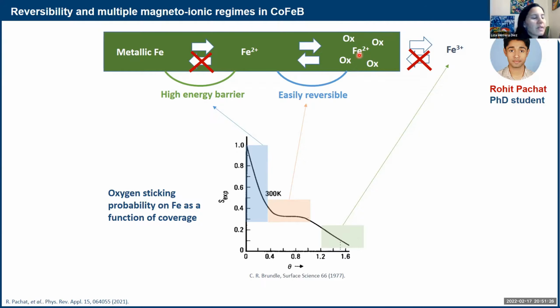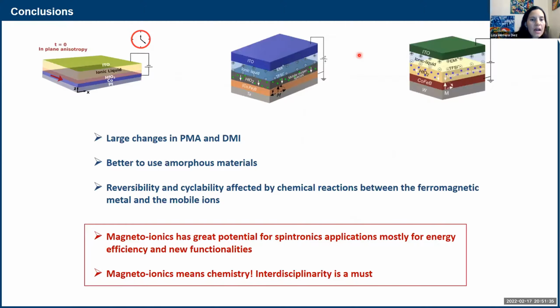I think it's very important to take into account what the ions do in the device. As a conclusion, I hope I could show you that we can get large changes in PMA and DMI by using magnetoionics. That it's better to use amorphous materials, because if we need ions to move around in the layer, we don't want them to be stuck or have a hard time going through a crystalline phase. And also that reversibility and cyclability are greatly affected by the chemical reactions between the ferromagnetic metals and the mobile ions. The ions are not just moving around, they're really modifying the chemical environment a lot wherever they are.